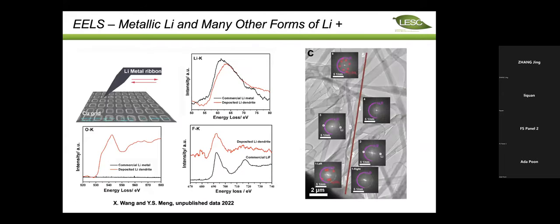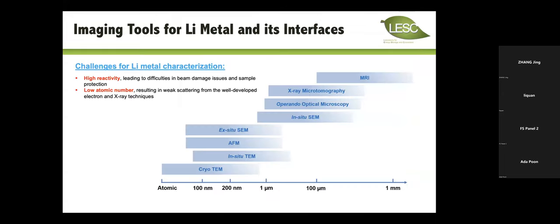And the heterogeneity of the lithium metal anode also imposes severe constraints on how we can analyze the data. So I just want to show you a very quick unpublished data that you can use concepts that are borrowed from the biology to do high throughput imaging and get a very good sample statistics, because it is indeed a very heterogeneous sample.